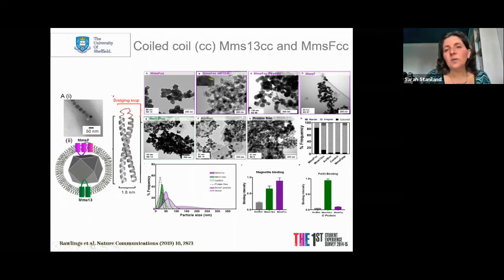So we did also do the reaction in the room temperature co-precipitation with just the peptide, just the loop region, and that had diabolical results. As you can see, the control over particle shape and size in this graph down the bottom is atrocious with the peptide. You get a huge range of sizes and lots of shapes. So it really does need to be constrained in this loop formation, which the transmembrane regions of the protein do in the membrane, and this coil substitutes for very nicely.